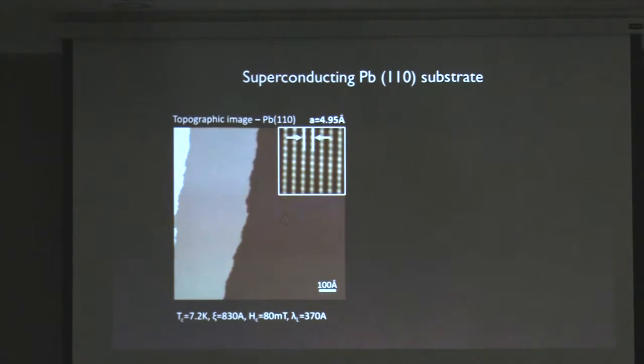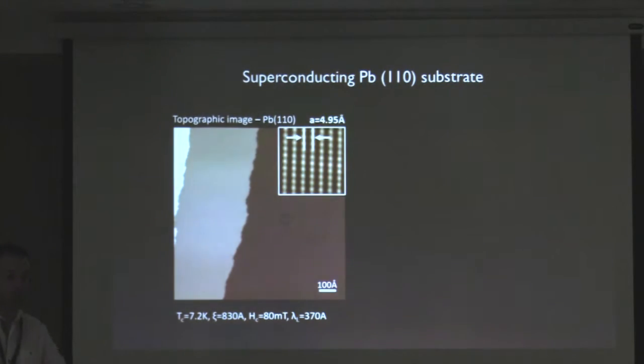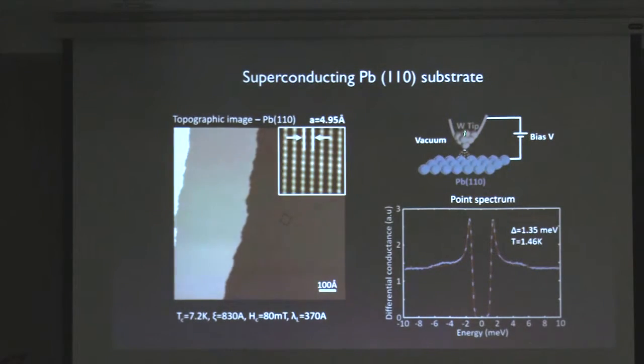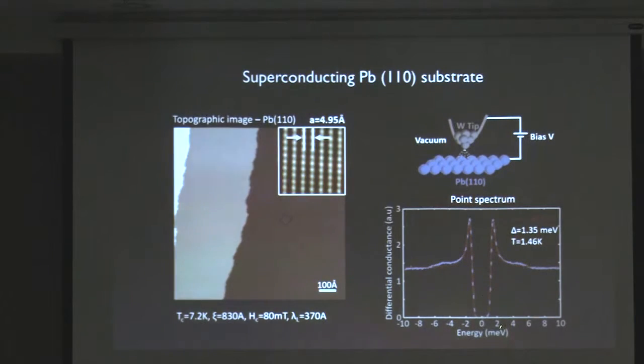You buy a crystal of lead with a polished surface, then clean it by heating and sputtering with argon ions to remove oxides and impurities. After doing this for about a week you get a clean surface, then find some nice flat spots. If you park your tungsten tip, open the feedback to keep the distance constant, and take a spectrum on any of these points, you get a nicely looking superconducting gap telling you the gap is 1.35 meV — as expected — and that you're measuring at about 1.5 K.